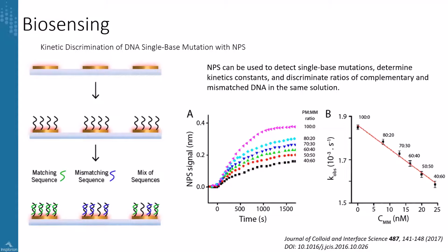And the mismatching sequence, of course, would not be as efficient in binding as a perfectly matching sequence for the same stringent conditions. As one expects, the matching sequence provides a perfectly good-looking binding curve, as you can see with the pink triangles corresponding to 100%, so exclusively matching sequence. But in this case, the mismatched sequence gave much poorer binding kinetics, so the researchers took it a step further and started measuring mixtures of mismatched and perfectly matched sequence.